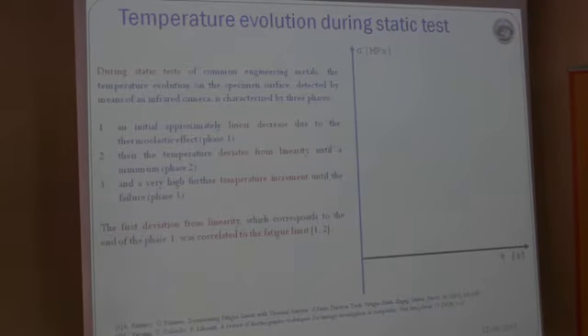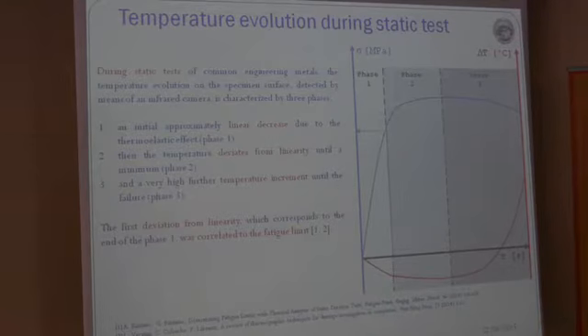During the static test, the surface temperature has three phases. First, an approximately linear decrease, the thermoelastic effect. After, there is a deviation from linearity, and the third phase is a temperature increment until the failure. For us, the first deviation from linearity is expected to correlate with the fatigue limit.